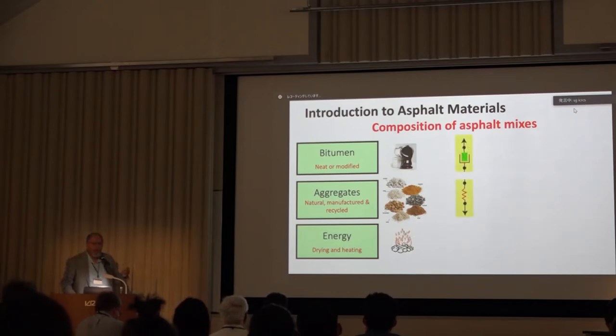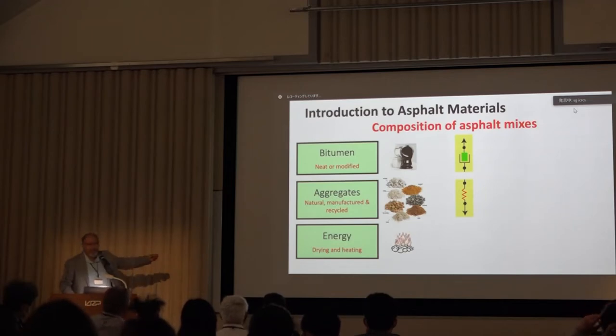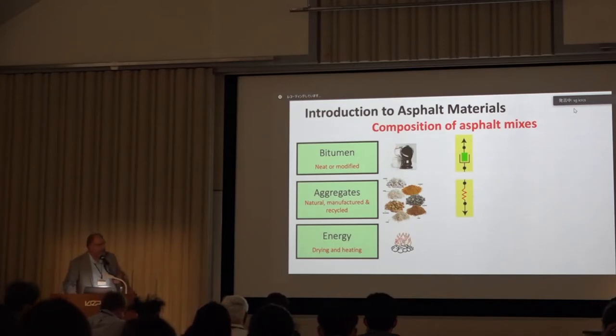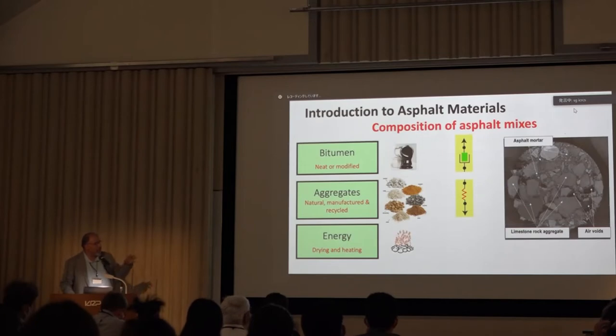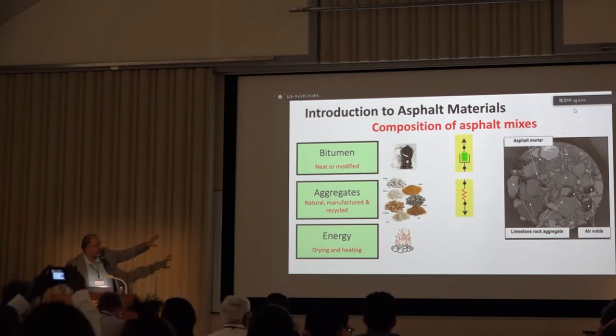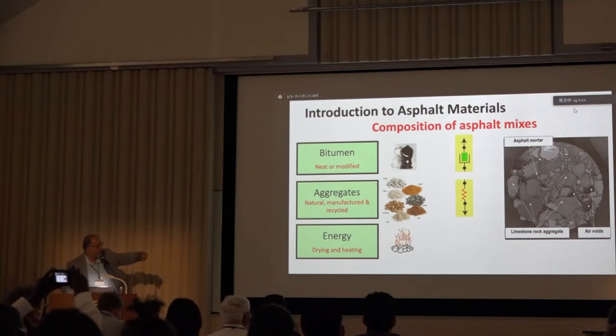And in terms of behavior, the components are very different. So we have the viscosity that comes from the asphalt cement, okay? Everything's called asphalt here. And elasticity, let's oversimplify, that's coming from the aggregates. So when we talk about healing, if we look at a slice with the microscope, we'll see the mortar, which is the bitumen mixed with the fine aggregates or the filler. We have limestone aggregates here, for example, and air voids.